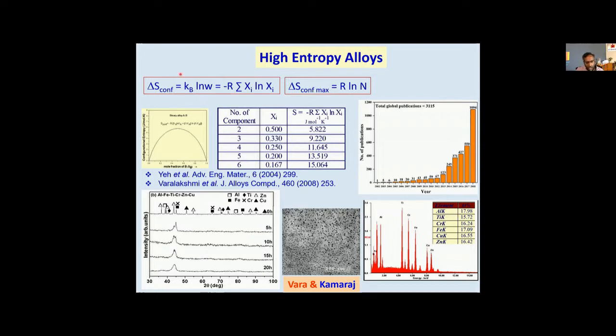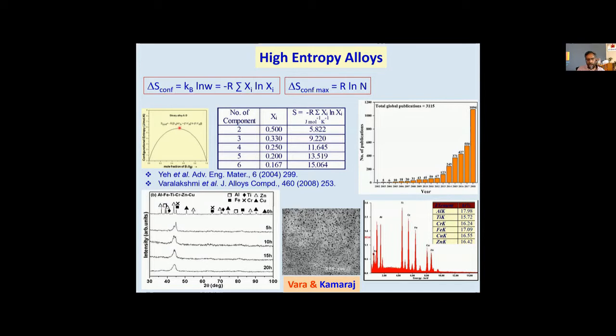If you expand this equation, it turns out to be minus R sigma Xi ln Xi, where Xi is what we call the mole fraction — the fraction of the element present in an alloy. If I plot this as a function of composition in a binary alloy, with A on the left side and B on the right side, you would see that as I increase the amount of B in A, the configurational entropy keeps on increasing and reaches a maximum at the center where A and B are in equal amounts. So when A and B are in equal proportion, the configurational entropy is highest.